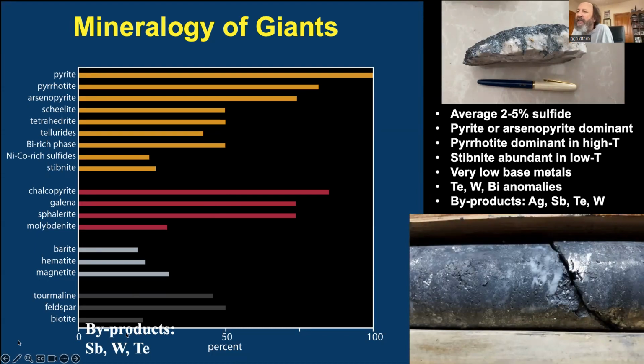The byproducts of orogenic gold, besides being just gold: antimony in the epizonal deposits can be very important. Two deposits in Northeast Russia, orogenic gold deposits, produce 10% of the world's antimony. Tungsten is very common in orogenic gold. Tungsten moves in orogenic gold in a metamorphic fluid because it comes from the breakdown of rutile. So if you have sediments that have rutile, you're going to have tungsten in an orogenic gold deposit fluid. And tungsten has been recovered from orogenic gold. And as tellurium gets more and more important, we're starting to recover tellurium from orogenic gold deposits because tellurides are present in most orogenic gold deposits.